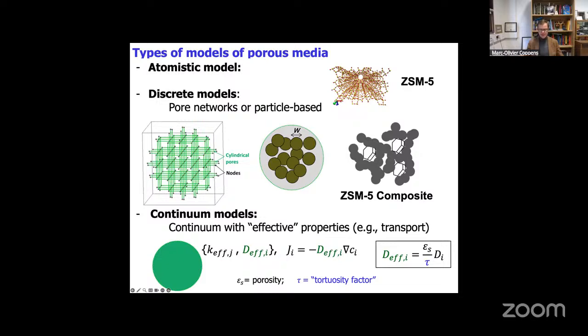The reality is that typically we have a mixture of gases. Of course, if you are in the Knudsen regime, the gases don't see each other, right? Since it's governed by collisions of the molecules with the walls, it is dominated by this. So Knudsen diffusion of a mixture is the same as the individuals. So at low pressures also, that's what you have. But if you start to have multiple components, then there is a description, the Stefan-Maxwell description of multi-component diffusion.